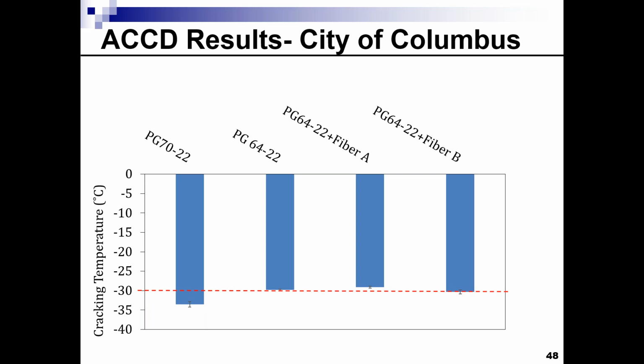cracking resistance. As you can see, the cracking temperature was minus 30, which is indicating that those mixes in general have good low temperature cracking resistance, but again, the fiber did not really affect that cracking resistance of the mix.